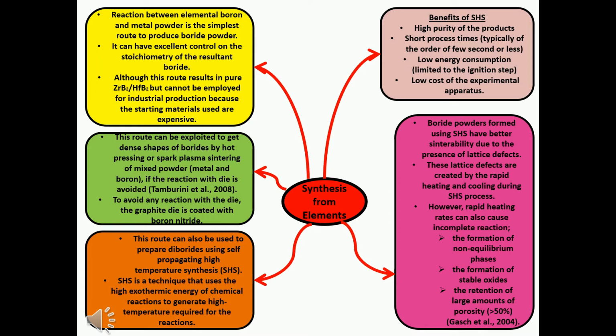This route can be exploited to get dense shapes of borides by hot pressing or spark plasma sintering of mixed powder, metal and boron, if the reaction with the die is avoided. To avoid any reaction with the die, the graphite die is coated with boron nitride. This route can also be used to prepare diborides using self-propagating high-temperature synthesis, SHS.